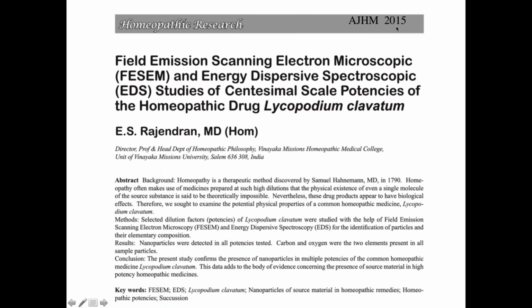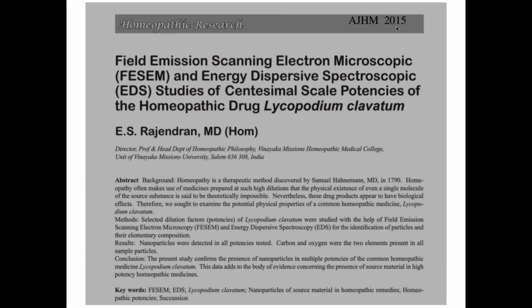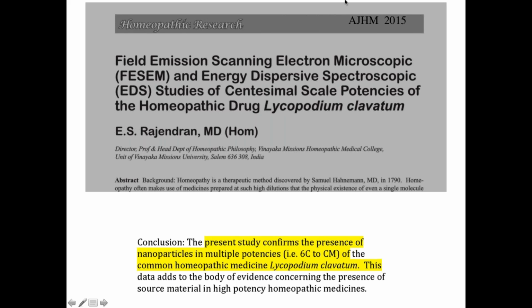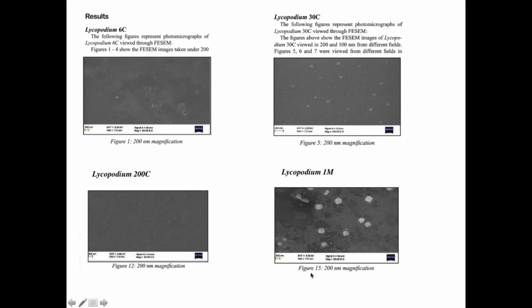Rajendran in 2015 extended our knowledge about homeopathic nanoparticles in homeopathic dilutions by, instead of using a metal, using Lycopodium clavatum, a very common remedy, a polycrest. And he didn't just use 30 and 200, he went all the way up to CM. And what did he find? The present study confirms the presence of nanoparticles in multiple potencies from 6C to CM.